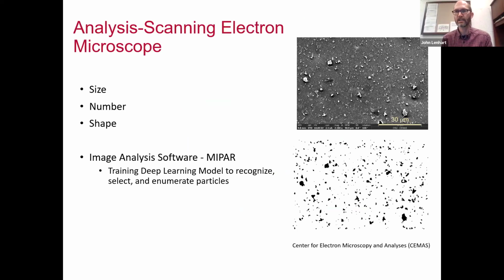Methods that we're using: we're using scanning electron microscopy. This gets us the size, number, and shape of the microplastics. And then to do specific enumeration, we're trying to develop an image analysis approach using a software called MIPAR. That's this image here on the lower right. We're training the model so that it can automatically identify the plastics and then do the counting itself, because visually doing it is very laborious. The image on the right is the model's perspective of the microplastics in the image on the top. It does a pretty good job. It avoids identifying a feature like this, which is actually a defect in the membrane. It's not a plastic, so that does not show up down there. So that makes us pretty happy.